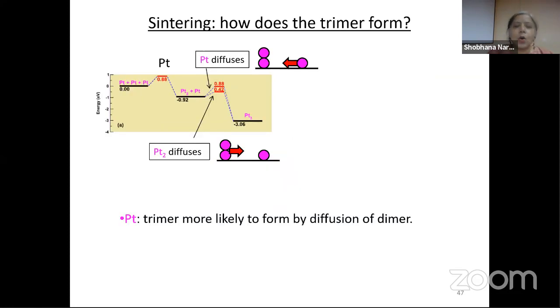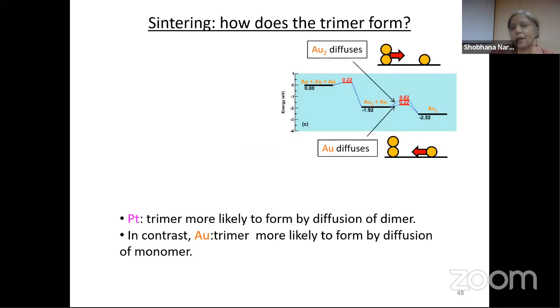Now, how does the trimer form? That's the simplest process we can look at. It could happen in one of two ways. You could have a single atom diffusing and joining a dimer, or you could have the dimer diffusing to join the monomer. Now, intuitively, you might think the above process should be lower in energy than the one below, but in fact, it is the other way. It is more energetically favorable in the case of platinum for the dimer to diffuse, because in the case of platinum, monomer diffusion is a very energetically unfavored process. However, in the case of gold, it is the other way around.